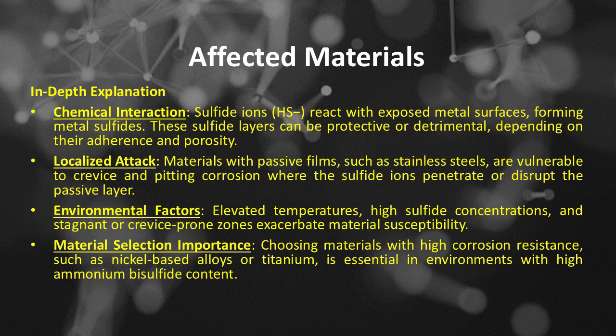In-depth explanation, chemical interaction: sulfide ions react with exposed metal surfaces, forming metal sulfides. These sulfide layers can be protective or detrimental, depending on their adherence and porosity. Localized attack: materials with passive films, such as stainless steels, are vulnerable to crevice and pitting corrosion where the sulfide ions penetrate or disrupt the passive layer.